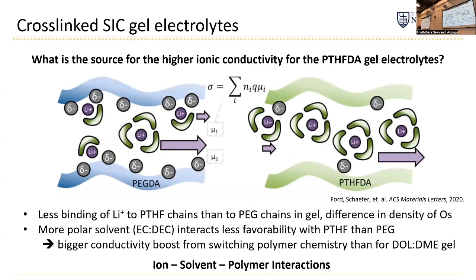And so the only way that you can explain this difference is how the lithium actually interacts with the polymer chain. And so what we hypothesize happens is this. In PEG, I told you that PEG is really an ideal lithium solvator. So we believe that even in the case when you have solvent in this gel, some of the lithium may be totally solvated by the solvent, and so it moves with vehicular motion unimpeded.